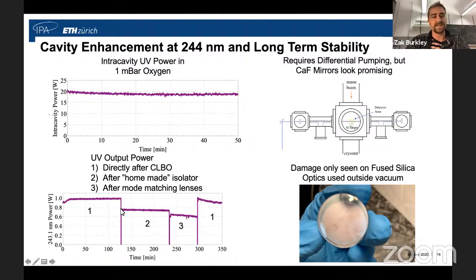You work so hard to make it, and through every optic, you lose a lot. It's a little bit sad, but that's life in the UV laser game. And then after some lenses, we take another hit, and we see the rate starts to degrade at around this 4 or 5 hour time scale. And we can take a look at pretty much all the optics leading up to the vacuum enhancement cavity have this damage on the coating.